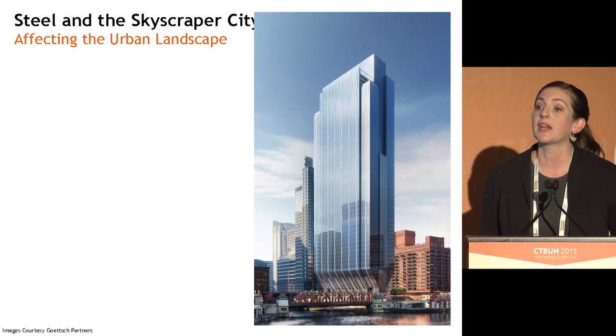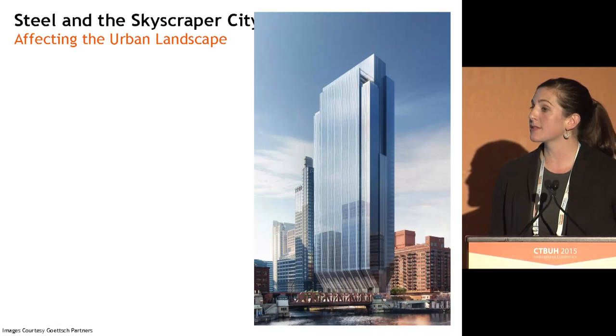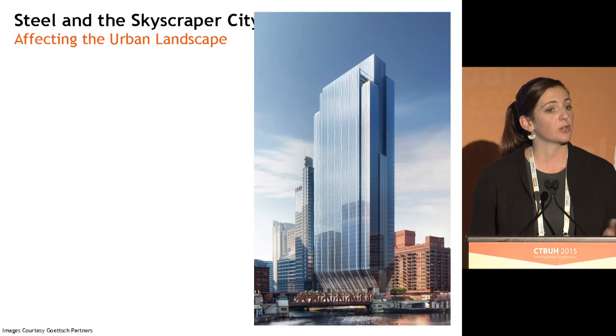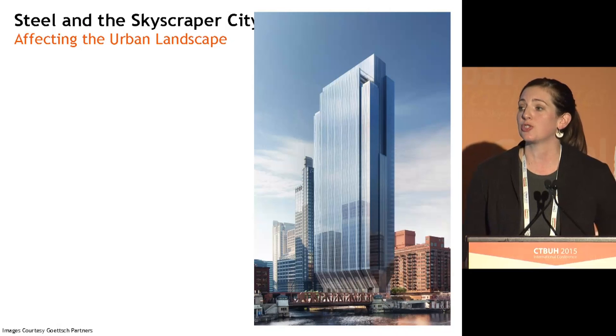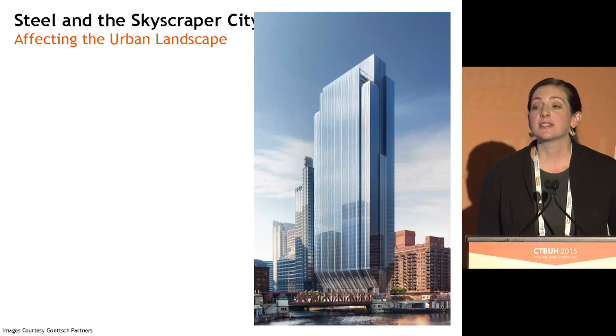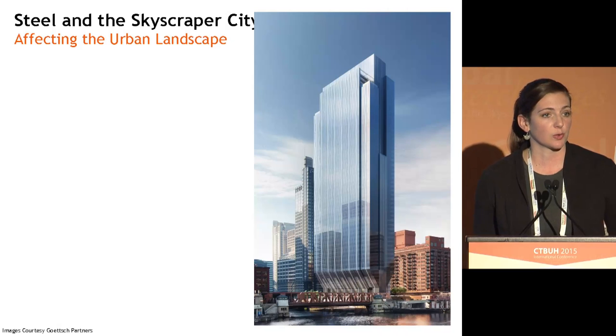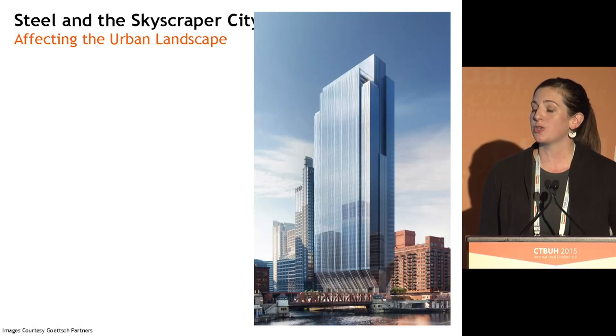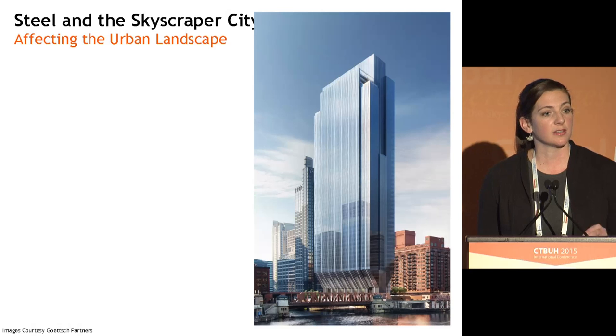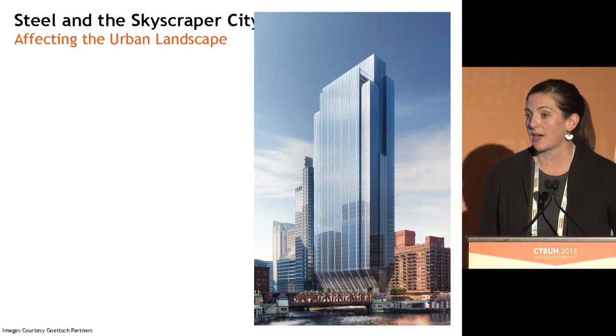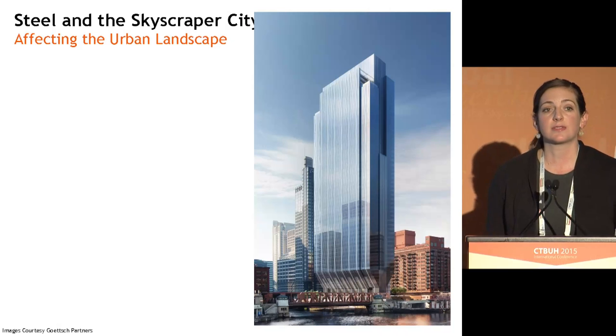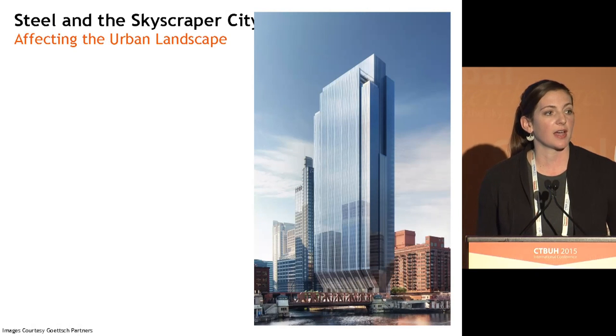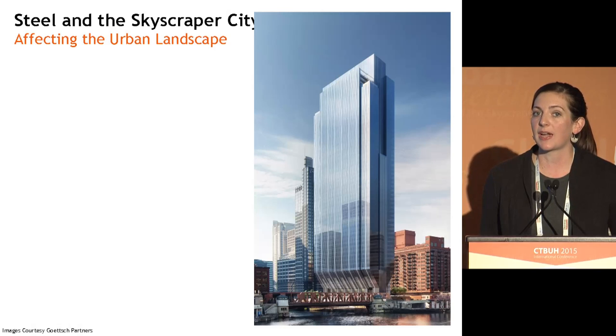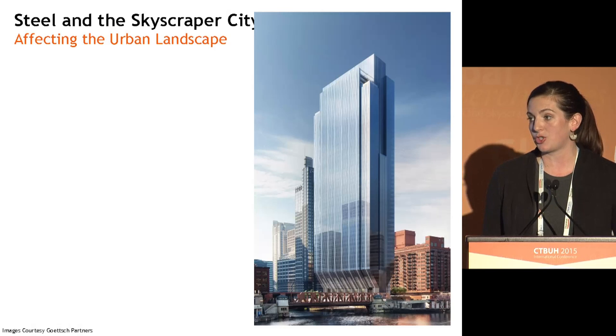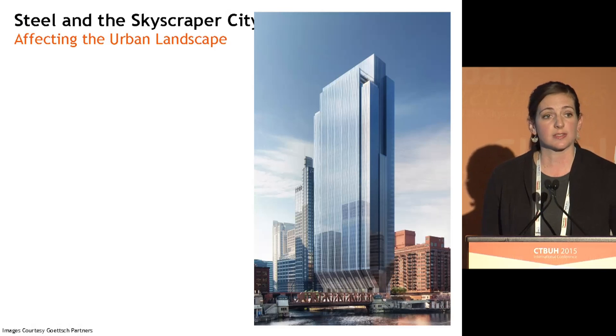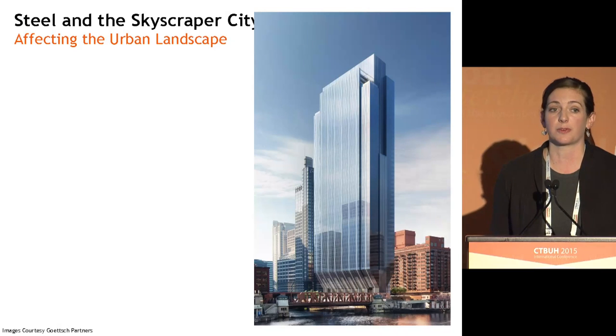And in addition to that, as buildings become more complex, such as the 150 North Riverside building, which perhaps some of you had a chance to hear about, I know Jim Getch was talking about it yesterday, this building has a very unique architectural profile, and in order to achieve it, the envelope of steel strengths had to be pushed as high as possible. So this building includes steel that has yield strengths of 65 KSI, steel that has yield strengths of 70 KSI, and it also uses some of the heaviest shapes in the world. Wide flange sections in this building go up to 925 pounds per foot.